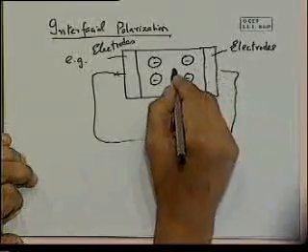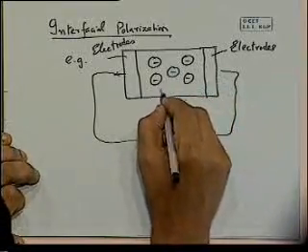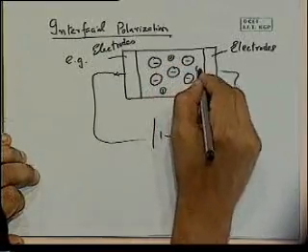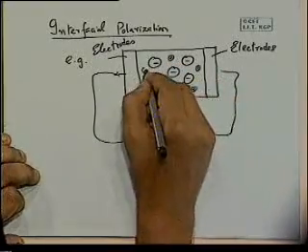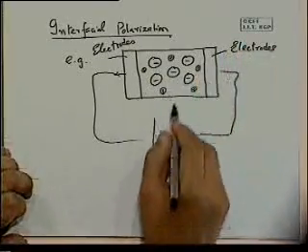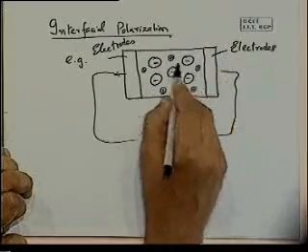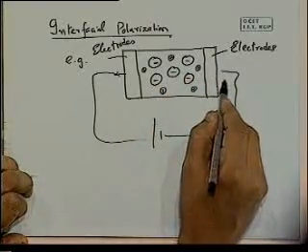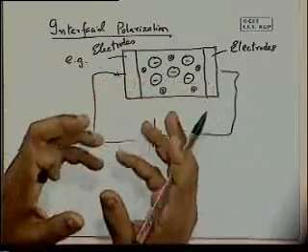So if you look at it, in some kind of dielectric electrode where we have species, say the negative species are more fixed, we can have structures like that, and the positive charges are more mobile as a result of their size, for example. I'll give you a specific example, 5 of them. So initially they're all balanced, you apply the field, and when you do that, these positive charges will migrate to this electrode because they can move through the network. They're very small, but the negative ones are more or less fixed.